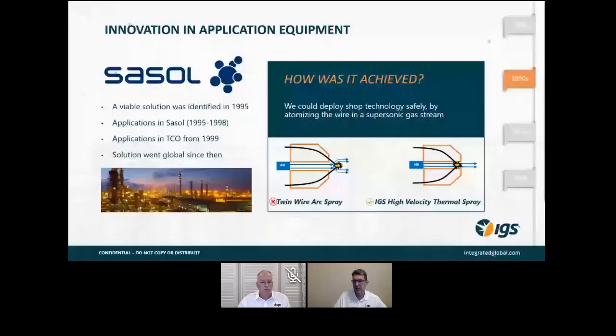And in essence, at a very high level, there's a much longer story, but what a couple of these smart engineers figured out how to do was to move the arc points. If you're looking at the slide, you'll see a schematic of a spray system on the left, which is the traditional twin wire arc spray system, which has been around since the 60s. Sometimes you'll hear the word TSA used in a system like that, standing for thermal spray aluminium. And what they did is they moved that arc point, which has traditionally been in a subsonic region of the gas, into a supersonic region. So they figured out how to get the arc point into the supersonic part of the gas stream.